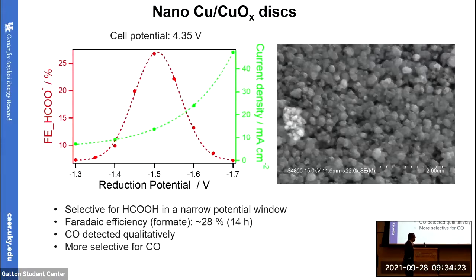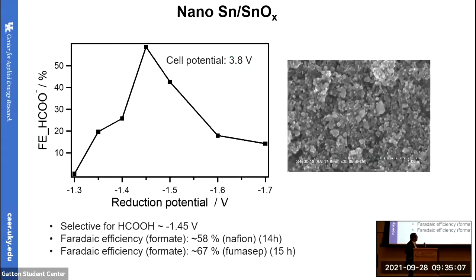So here is the result from the copper oxide nanodisks. This is the Faraday efficiency for formate ion as a function of reduction potential, negative 1.3 to 1.7, and this is the corresponding current density. We are using this catalyst. We got a Faraday efficiency of 28% in 14 hours, and it produces formic acid in a very narrow potential range, about negative 1.55. Literature also reveals that this catalyst is very selective for carbon monoxide, but it does produce formic acid to some amount. So then we synthesized and tested tin oxide nanoparticles.